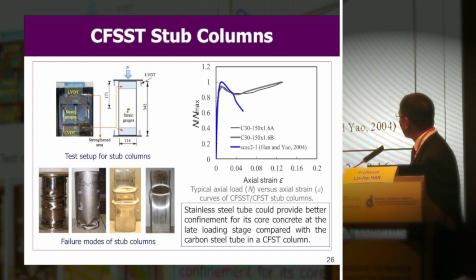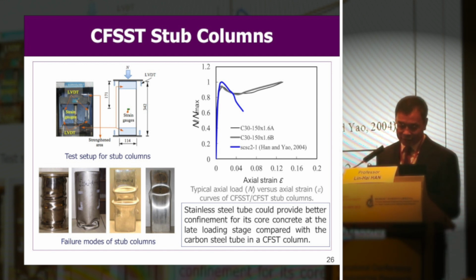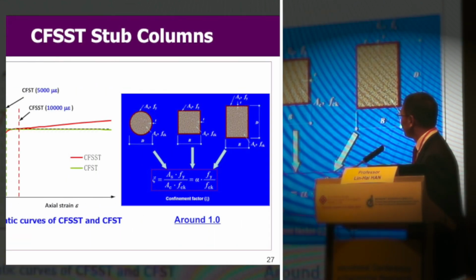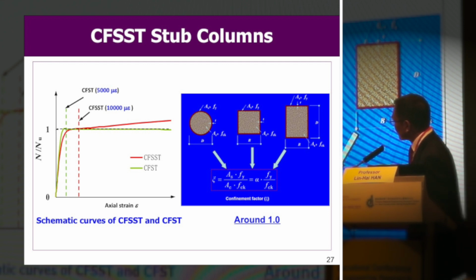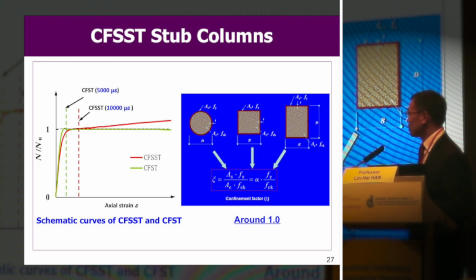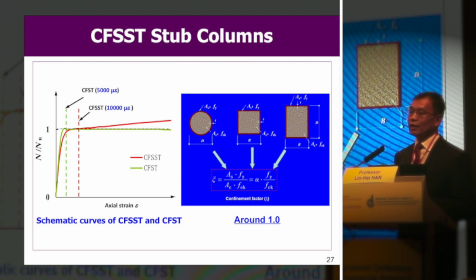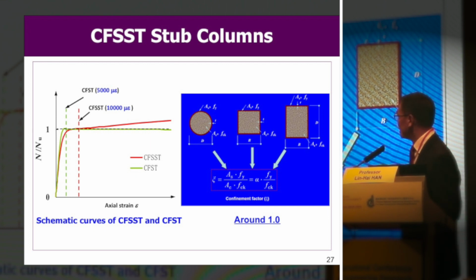So this means for concrete filled stainless steel tube, at the later stage, the steel tube can provide a better confinement compared with the carbon steel tube. And this is a very important factor. So it's a confinement factor actually for concrete filled steel tube. This is the only equation in this presentation. You can see this ratio actually can reflect the effects of the core concrete and also the outer steel tube. The denominator is the concrete area and the concrete compressive strength, and the numerator is the area of outer steel tube and the yielding strength. So the higher this ratio means the higher confinement that the steel tube can provide to its core concrete.